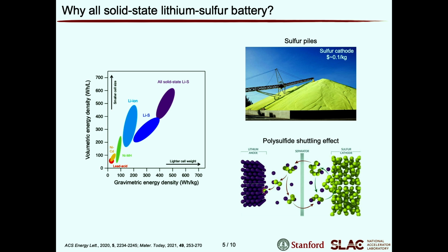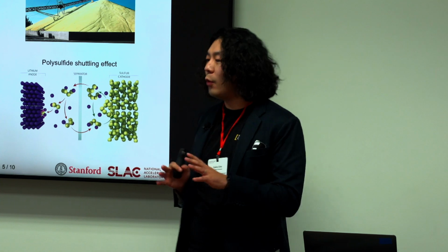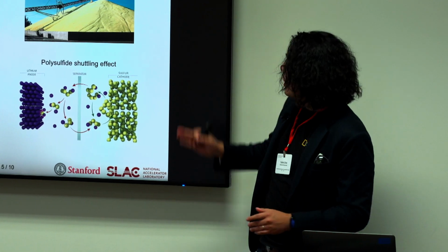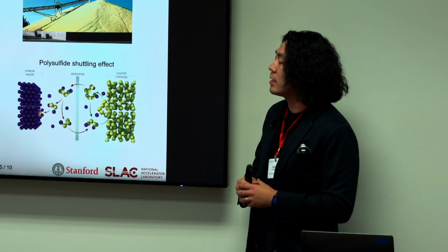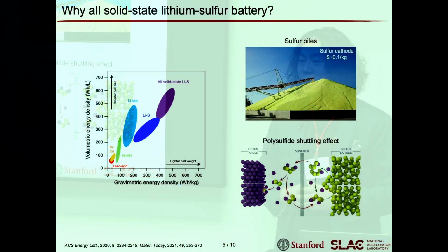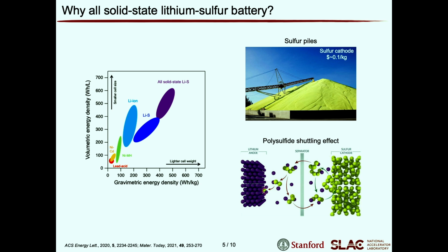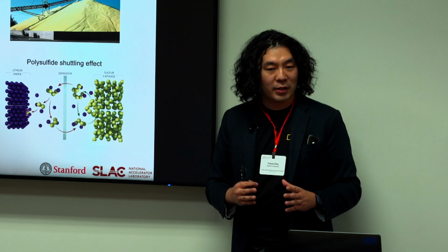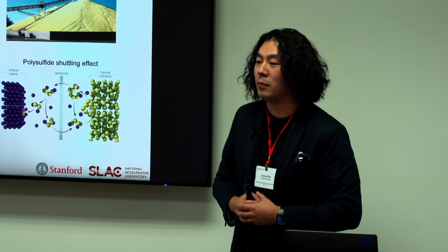The reason I'm looking at lithium sulfur is not only that it has a higher energy density, but it's very cheap. Sulfur is a byproduct of copper mining, and people usually want to get rid of it. I put a number here: sulfur cathode is usually about 10 cents per kilogram. Just to give you a sense, for NMC, LCO, any kind of metal oxide cathode we are using today, it's about $20 per kilogram, even at state-of-the-art industrial scale. So you can see there is a difference of hundreds of times. And in actual battery manufacturing, 50% of the cost is from the cathode materials.